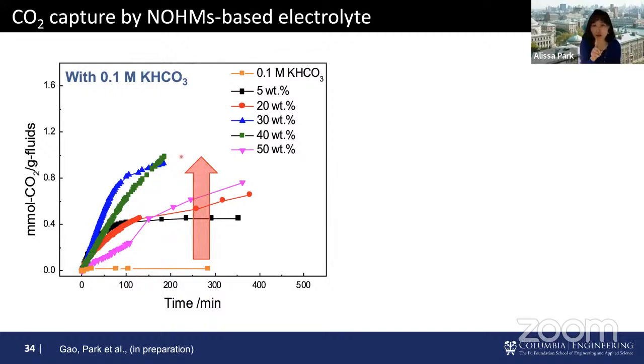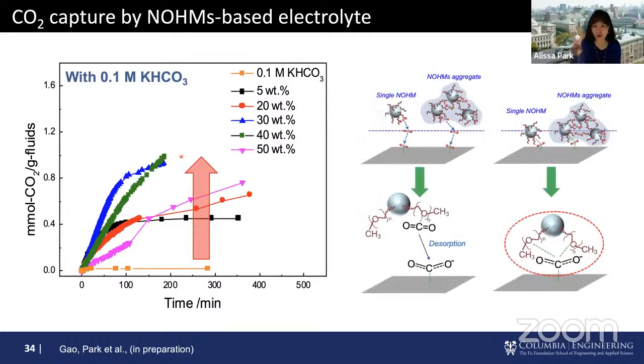But this led to a lot of interesting discussions because, as shown here, CO2 loading is higher, but how is CO2 delivered to the surface of the catalyst? Our hypothesis is that, because Faraday efficiency with and without NOHMs was slightly different, in some cases quite different, one mode of CO2 delivery to the surface of the catalyst is NOHMs serving as an internal reservoir of carbon, releasing that CO2, and that released CO2 gets adsorbed to the surface of the catalyst. That should not change the Faraday efficiency.